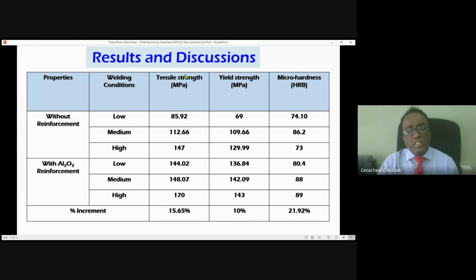When it comes to the results and discussion, the results have been compared between the joints in terms of tensile strength, yield strength, and micro hardness. The table discloses the comparison between the joints without reinforcement and with alumina reinforcement. We can see the improvement in tensile strength as high as 15.65%, for yield strength 10%, and for micro hardness in HRB scale 21.9. So this is a promising result associated with the addition of the alumina particles